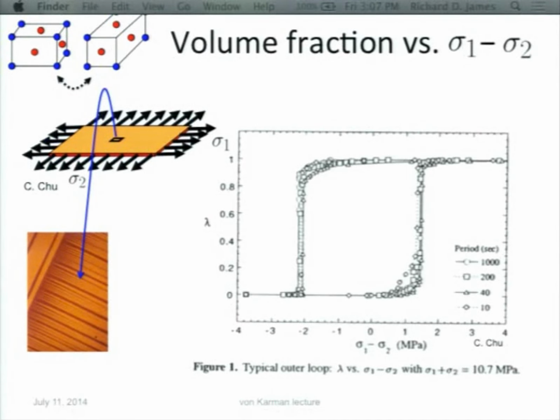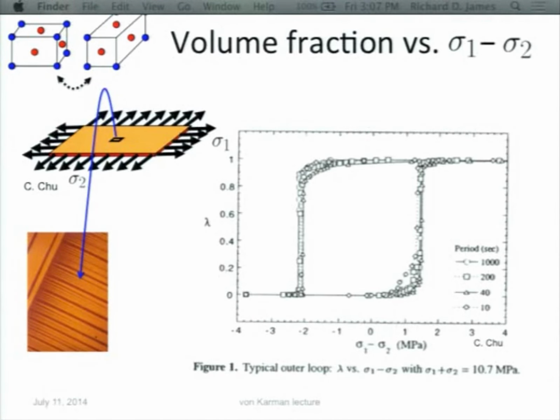So a key thing about hysteresis in these diffusionless phase transformations, which is quite surprising actually, is in that stress-induced case. If you go back here and look at this case, this is that hysteresis loop, and it was done by loading this crystal in a biaxial way. I won't describe how it was done. The percent of one variant versus another was measured by taking a window on this picture and computing the area fraction of the colors.